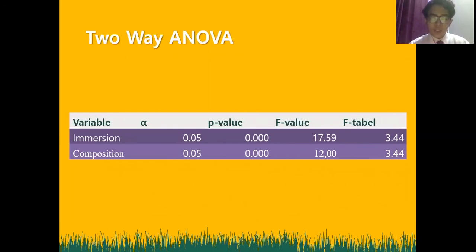On the composition and immersion variable, the p-value is smaller than alpha, and F value is greater than F table. Besides, on the result of ANOVA, there is a rejection of H0 in both independent variables. So it can be concluded that the immersion time and composition affect the tensile strength.